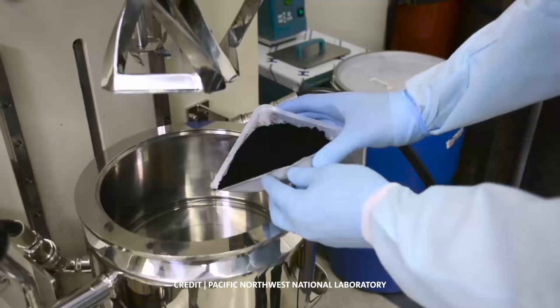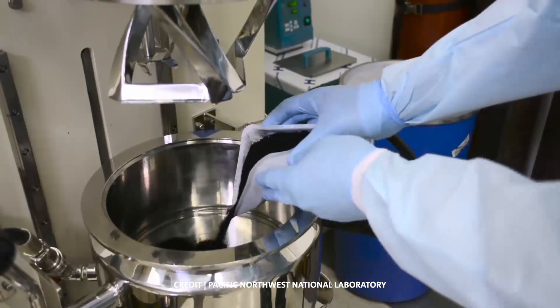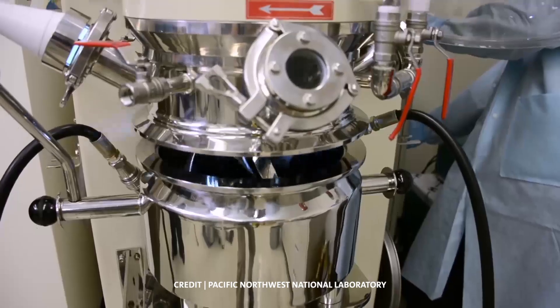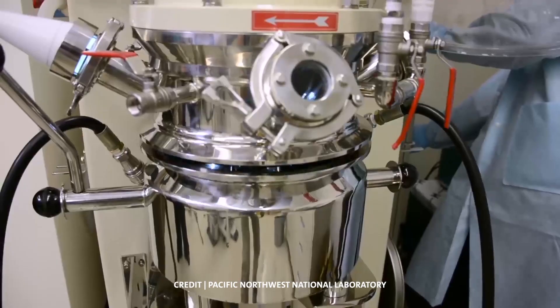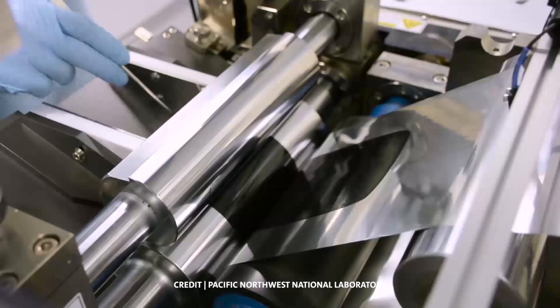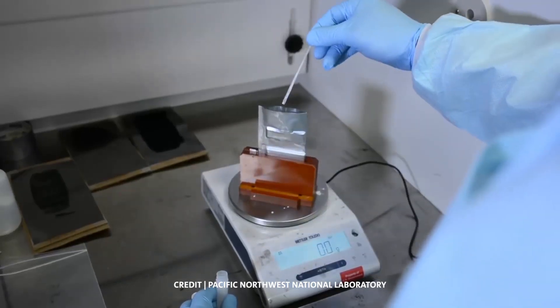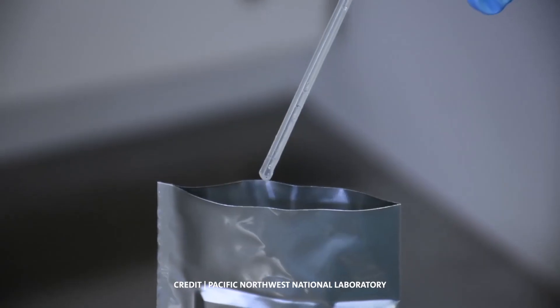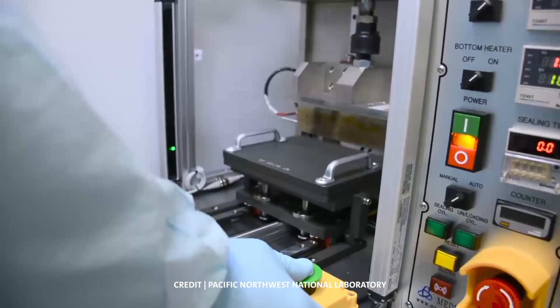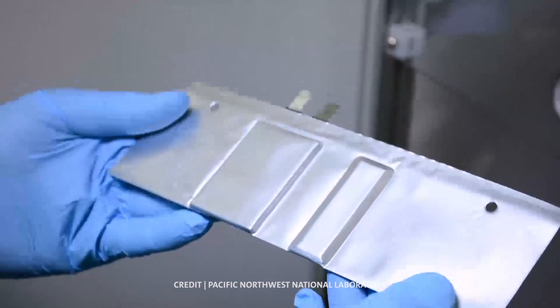For example, manufacturers should confirm that no metal or foreign particles enter the electrode paste when it is being mixed or applied to current collectors. Ensure that the electrode paste is coated into the current collectors uniformly, without gaps or bubbles. Add an accurate volume and high-purity electrolyte to cells, and use proper sealing techniques for pouch and cylindrical format cells.